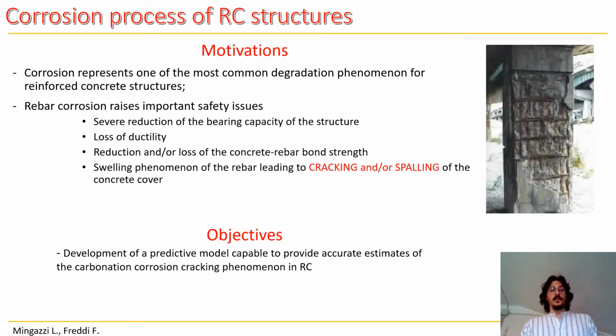We decided to focus on this topic because the corrosion of reinforcement bars is one, if not the most, common degradation phenomenon for reinforced concrete structures. Due to the corrosion process, the cross-section area of the rebar suffers a reduction, which translates into several safety issues that might arise in the structure, such as a reduction of the bearing capacity, a reduction of the ductility, and a reduction and/or a complete loss of the bond between the concrete and the steel rebar.